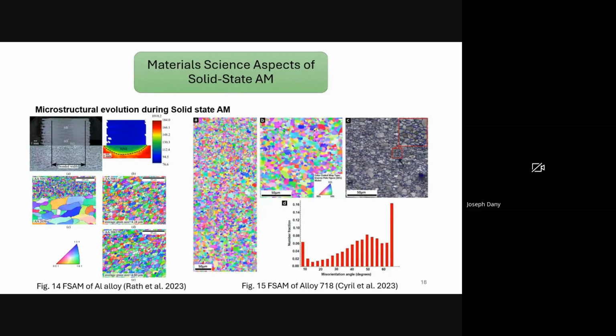This microstructural refinement is not just of academic interest, but has important implications for properties. A fine grain structure with a high fraction of high angle grain boundaries enhances strength through the Hall-Petch effect, improves toughness by disrupting crack propagation, and provides better resistance to fatigue. However, it is also important to note that while fine grains are beneficial at room temperature and moderate temperatures, for very high temperature applications such as those faced by nickel-based superalloys, extremely fine grains can sometimes promote grain boundary sliding and reduce creep resistance. Therefore, the balance between grain size and high angle grain boundary fraction must be carefully considered depending on the intended service condition.